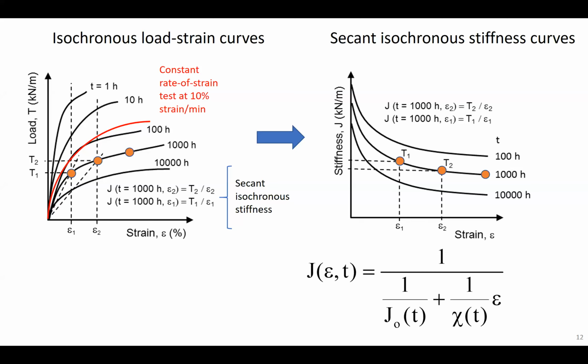And this formula, as you see it here, has two components. One is J naught, which is the intercept of these curves with the vertical axis. And the chi term that you see here is a quantitative measure of the magnitude of the curvature. So once we have this equation for each of these isochronous stiffness curves, we can then put it into an equation where the secant stiffness times the strain will give us the load that is predicted at that strain and that time.